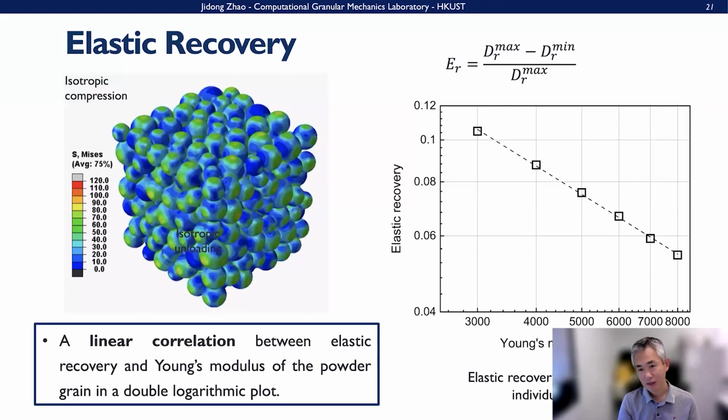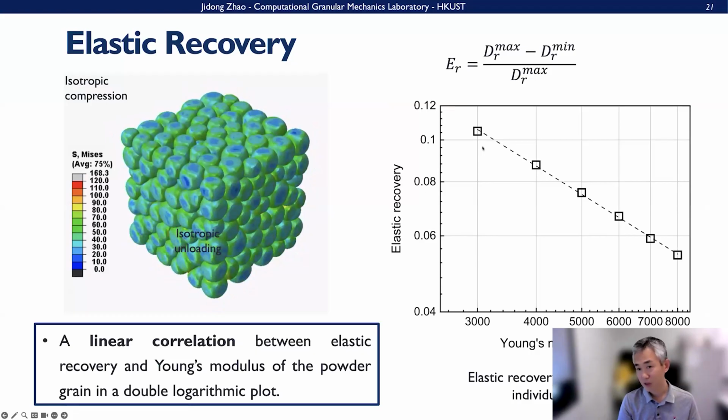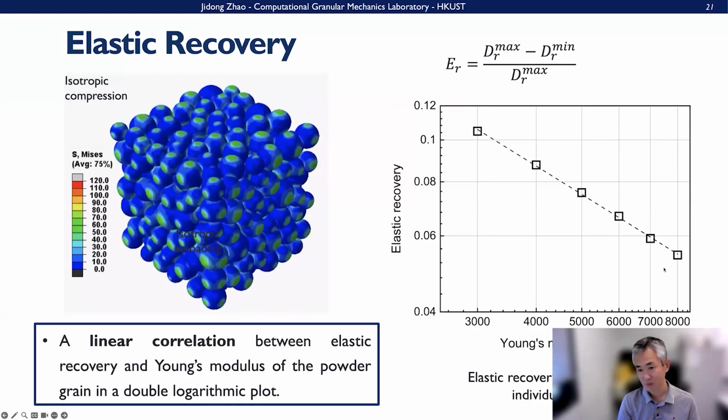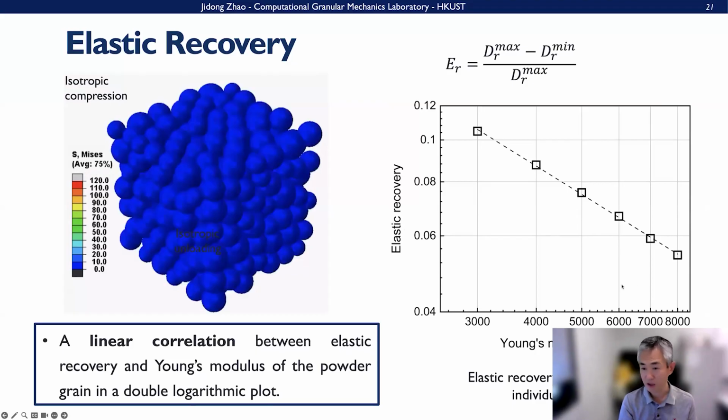We observe a nearly perfect inversely proportional linear relationship between the elastic recovery and the Young's modulus of the particles here.